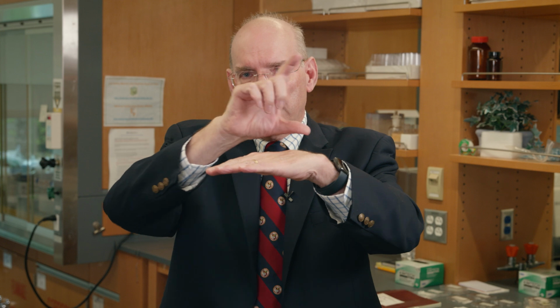And sputtering works in this way. You start with a block of solid chrome, you put a gas in here, and you turn it into a plasma. You basically strip off the electrons, makes the gas atoms charged, and then you can use the charged atoms, accelerate them into the chrome target, and then knocks the chrome atoms out, and they drift back through the plasma and land on the substrate where you're trying to grow this film. This is a complicated process. It has lots of different parameters that you can control, but you can make a chrome coating, and you can control the properties of that chrome coating over quite a range.